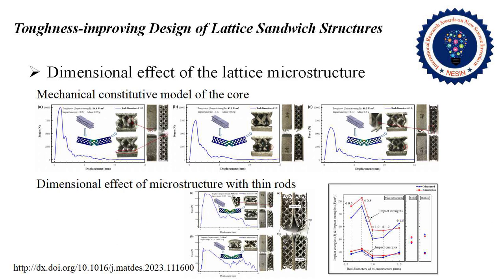It is interesting that the structure with thin rods has a dimensional effect. With this effect, the core and the skin could synergistically improve toughness. When the rod diameter decreases continuously, the stiffness and bearing capacity of the core are reduced rapidly, and the impact loads are difficult to effectively transfer from the top to the bottom of the sample. As a result, the stress value of the bottom skin is low, and the intensity factor is smaller. Therefore, the fracture toughness of the bottom skin decreased.